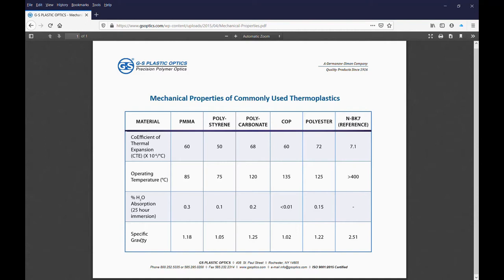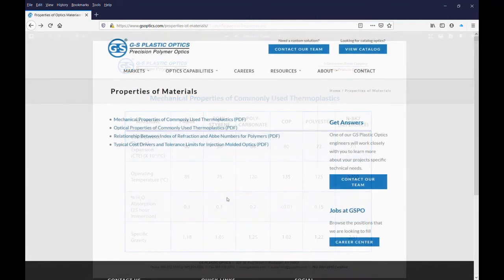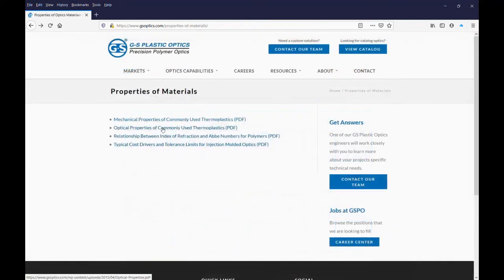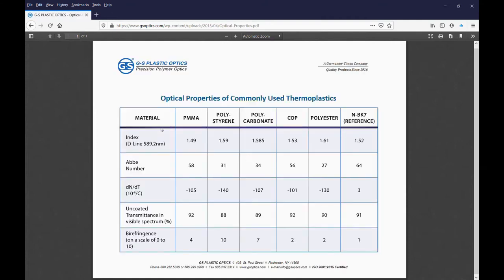Optical designers should note high thermal expansion of the thermoplastic resins. It's about an order of magnitude higher than glass. Thus, maintaining focus over a wide temperature range is a significant problem. They should also consider maximum sustained operating temperature and water absorption of the selected materials to make sure they match product application. The optical properties of commonly used thermoplastics document includes index, Abbe number, dn/dT, transmittance, and birefringence data.